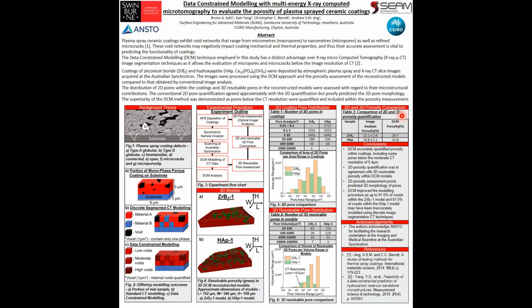However, it was found that the 2D quantification of porosity within the coatings via image analysis was in moderate agreement with the total porosity determined within the 3D models. The difference in porosity quantifications is due to the superior ability of the DCM methodology to quantify fine structure details of micropores and cracks over 3 dimensions as compared to 2D image analysis.